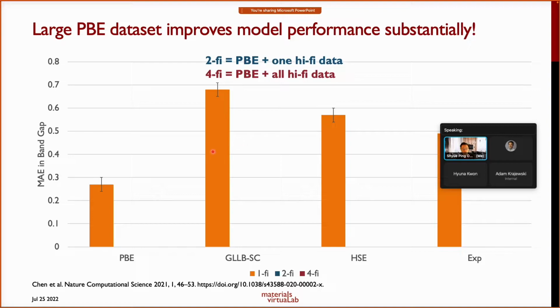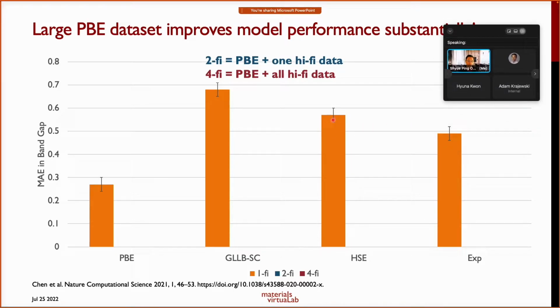Okay, so let me first show you what happens when you try to build a MEGNet model with just a single set of data of the band gaps, right? So you notice that the mean absolute error of the PBE data is close to 0.3 eV. Okay, so we can predict the PBE band gap to within 0.3 eV or so. However, the errors on our HSE and experimental band gaps, which are really what we want, are much higher, right? Our HSE band gap error is greater than 0.5 eV. Our experimental band gap error is close to 0.5 eV, right? When we just build our MEGNet model using each of these data sets in turn.